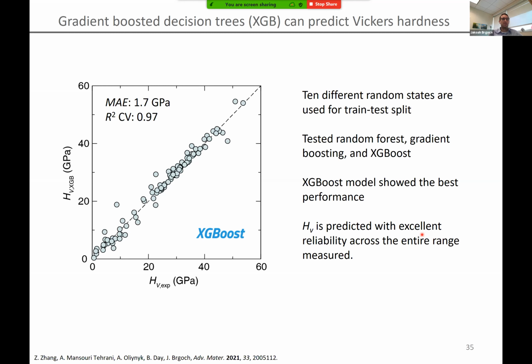Overall, our model is really outstanding. Our R squared is 0.97, and the mean average error is 1.7 gigapascals. This is notable because experimental measurements on hardness generally have about 10% error. So overall, across the entire range, we're doing really well.